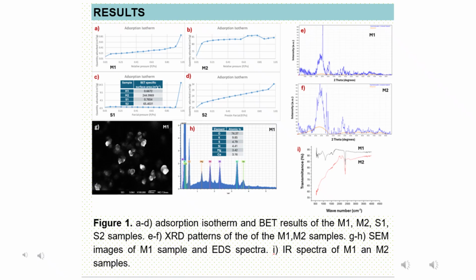FTIR spectra show characteristic vibrations of oxygen-hydrogen bonds, double carbon-oxygen bonds, and single carbon-oxygen bonds groups in M1 and S1 samples. These indicate the presence of oxygenated functionalities. On the other hand, in the samples with high temperature, the intensity of these peaks decreases. This reflects the progressive carbonization and removal of surface groups. This trend correlates with the increase in the surface area and the possible development of more stable aromatic structures.